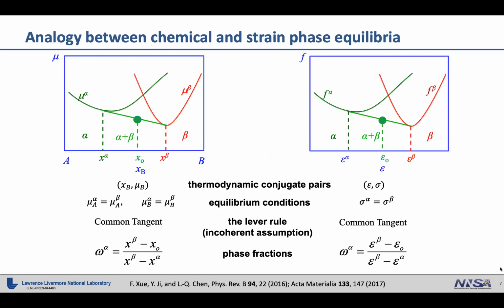So our initial attempts have been made by my previous colleagues, and their attempt was based on a few observations. First, the strain and stress are thermodynamic conjugate pairs, just as the composition and the chemical potentials. And also the chemical equilibrium condition, which is a uniform chemical potential within the system, can be drawn in analogy with the uniform stress component.